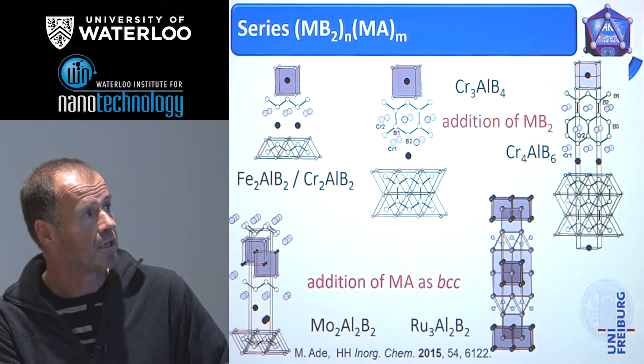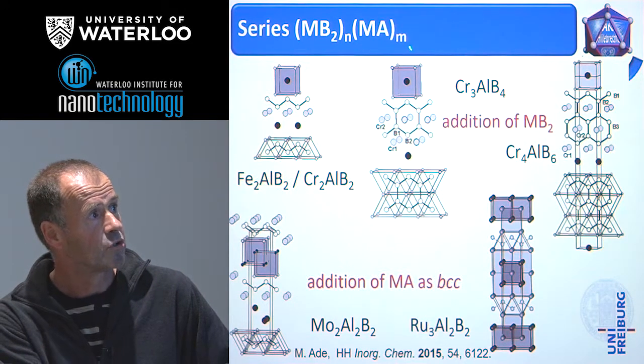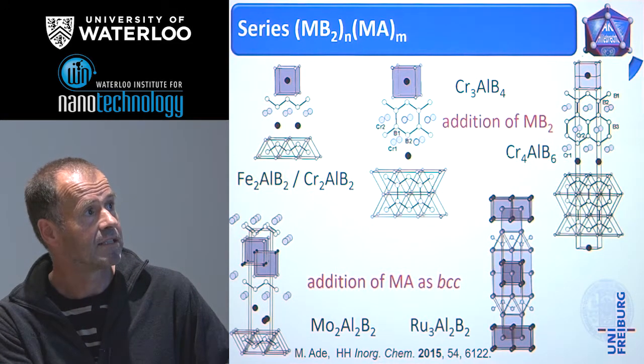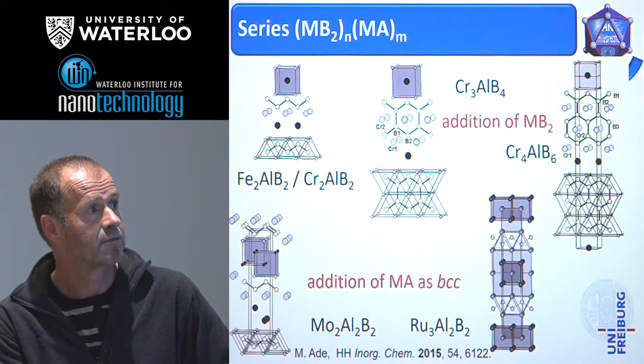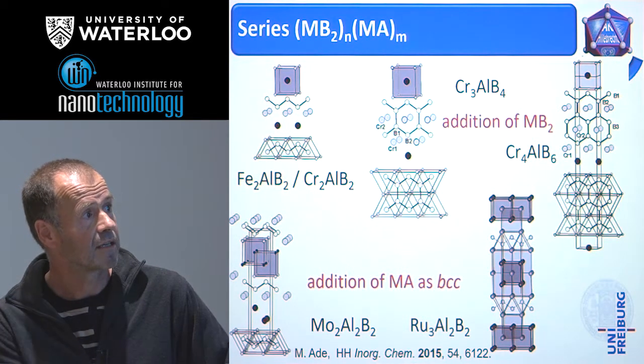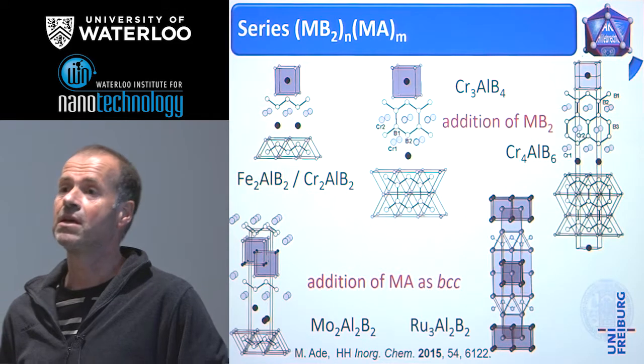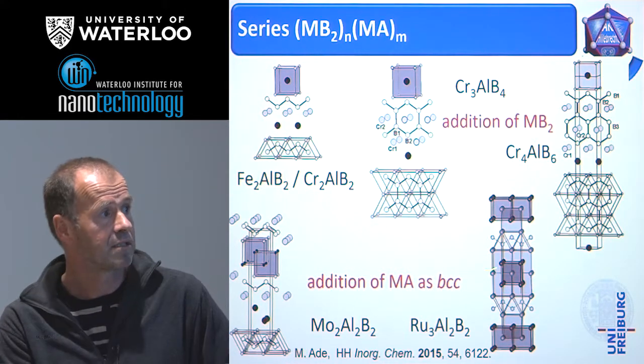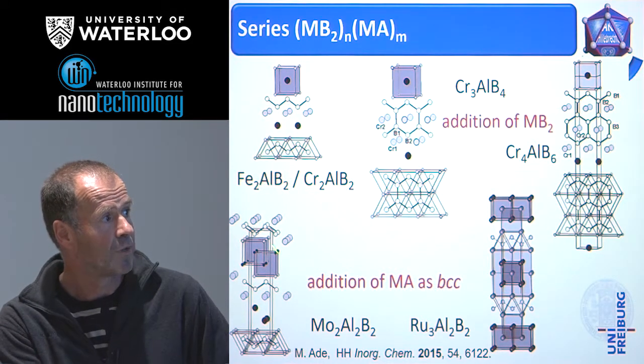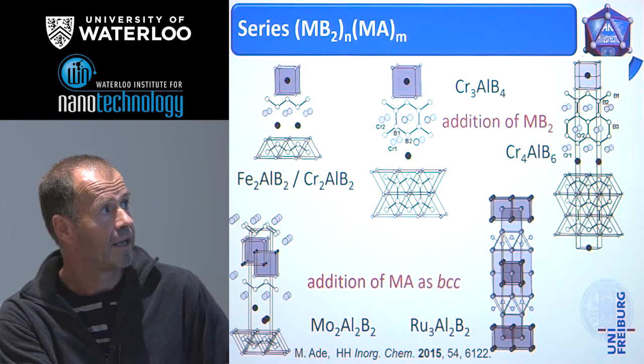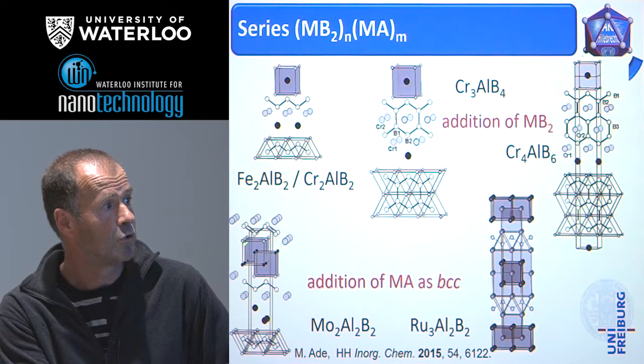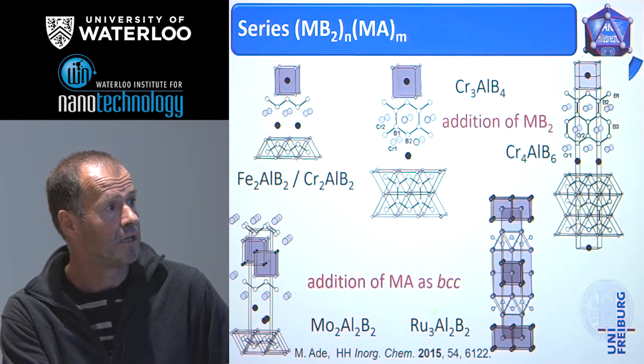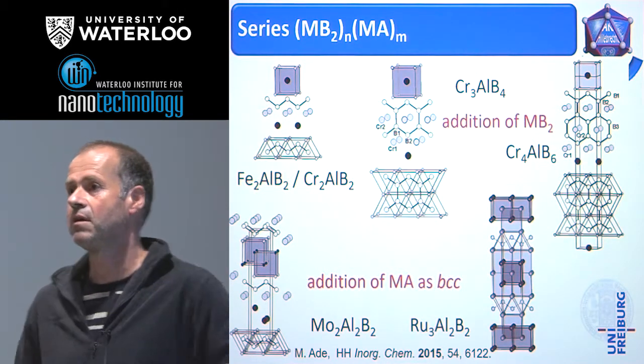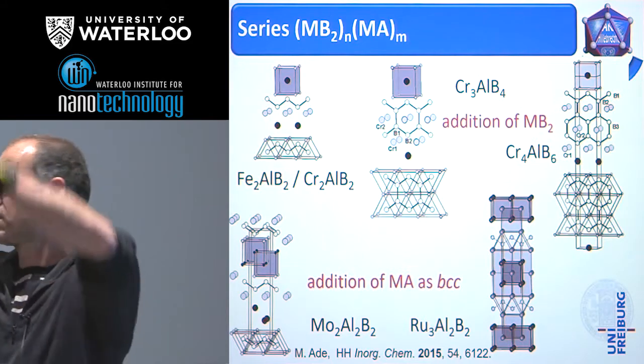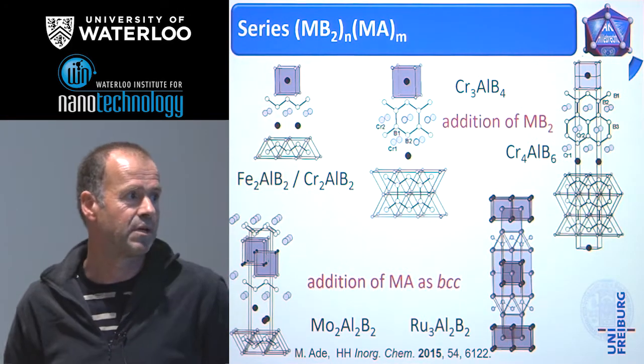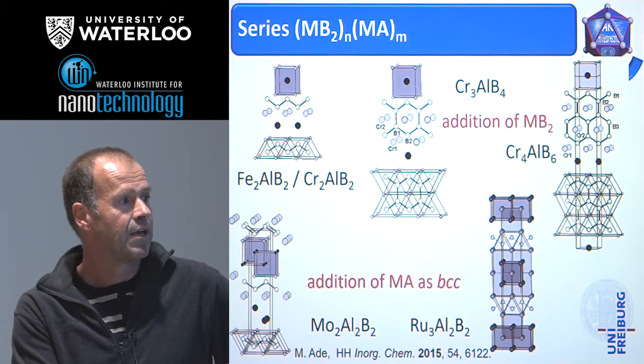And by additional boron content, you just increase the size of the boron substructure by additional zigzag chains, or you can also increase the share of the intermetallic part as a BCC form. You see here we have one layer of intermetallics, here we have two intermetallic layers, and here we have three. Just like a toy, you can just build it up. This building principle was generalized in this publication.